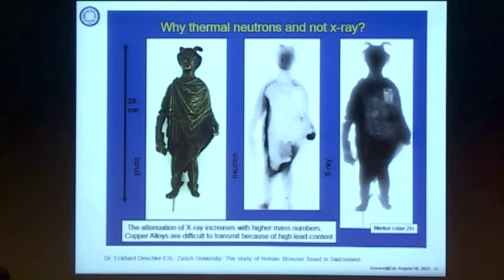This is another sample of a sculpture which again demonstrates the difference between neutron and X-ray imaging. On the right-hand side, we can see X-rays. Again, this is quite an opaque object for X-rays. But on the left, you can see that neutrons reveal different contrast in that object, and they can show where things were added at a later time, because, for example, bronze composition changed in different centuries, there's different bronze composition, and you can tell the differences